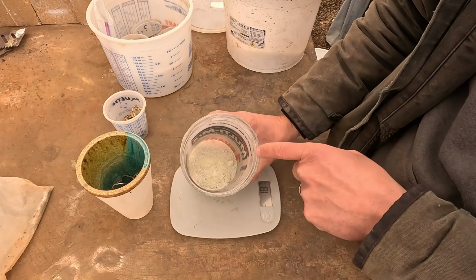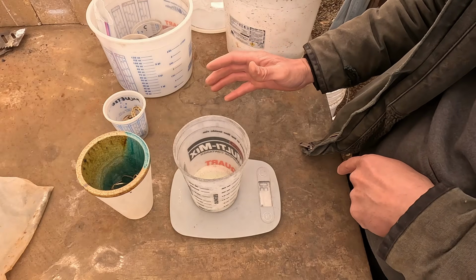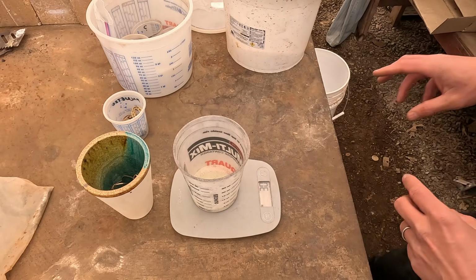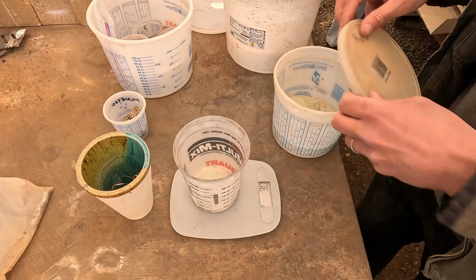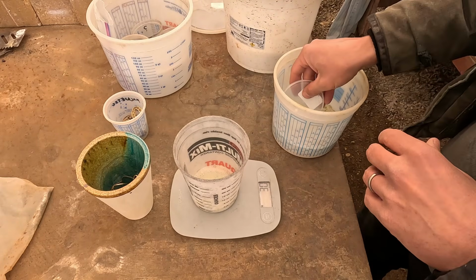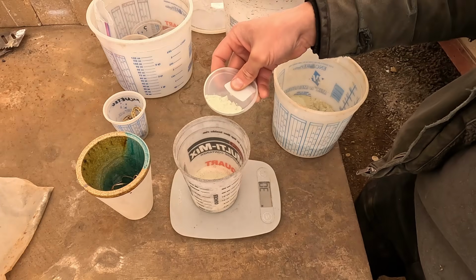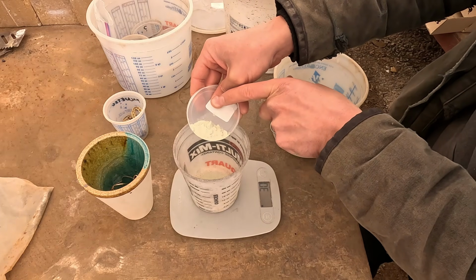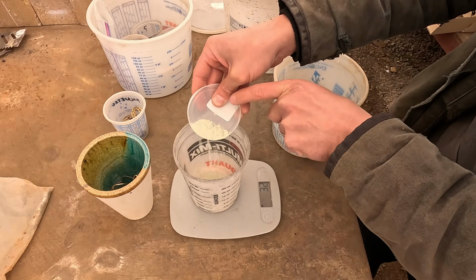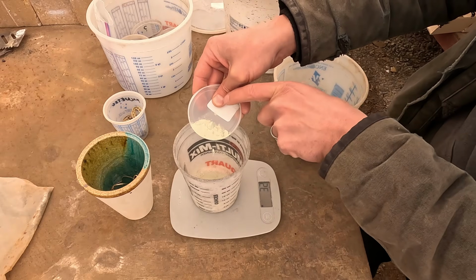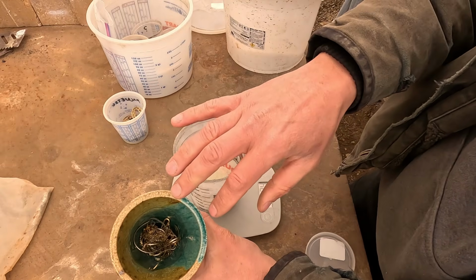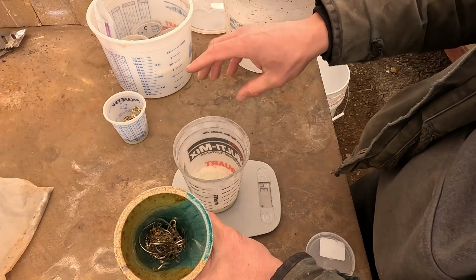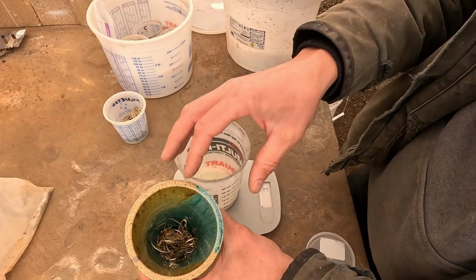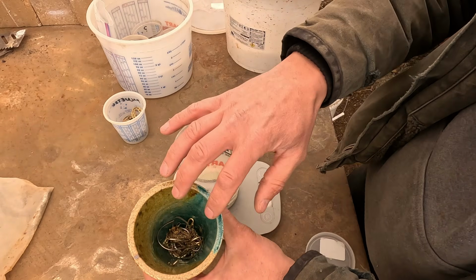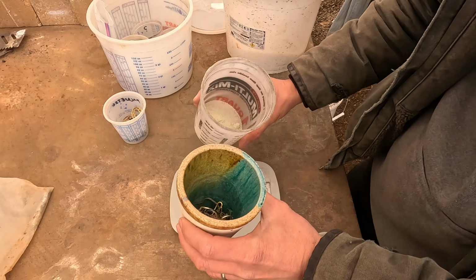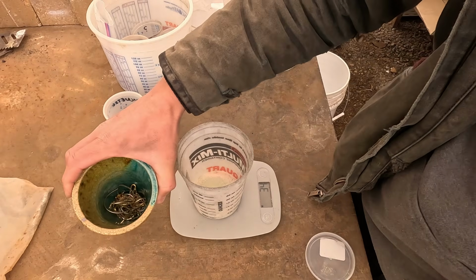And so I'm gonna add in 30 grams of bismuth. What did I put in, 30 grams? About 30 grams, I need about 33. I'm gonna add a couple more. But the bismuth oxide, when it touches the gold fill and the copper and the iron, it will turn into bismuth metal, and it will oxidize the iron and the copper and the zinc, and that will go into the slag. And so what we should have is all this base metal get oxidized away. The bismuth will reduce, collect everything at the bottom, and then we'll have all that junk in the slag and just our precious metals in the bottom with bismuth that we can get rid of.